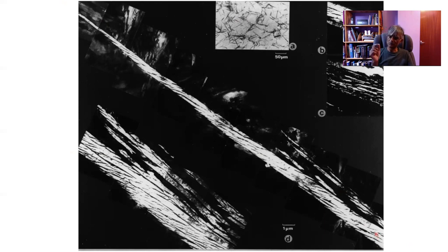And the important point I want you to notice from this is that the length of a platelet and the thickness of a platelet at the beginning here, near the austenite grain boundary, is the same as near the tip of that cluster of platelets, right? So these platelets are growing to a size of roughly 10 micrometers and getting halted by mechanical stabilization. So you have to form a new platelet and new platelet and new platelet, and the whole sheaf evolves in the form of a plate, because again, that minimizes the overall strain energy, a very, very clever struggle that bainite goes through,